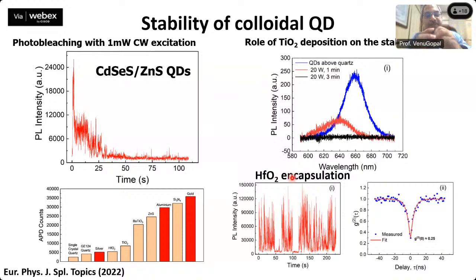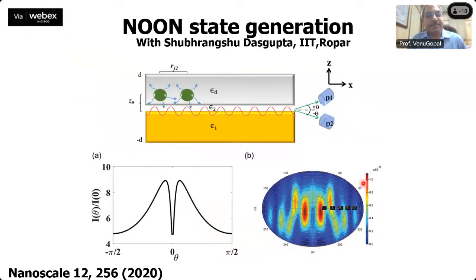Blinking happens for these nanoparticles because the surface is a defect. Any electron which reaches the surface state stays there for a long time, and because of that the emission gets suppressed for a certain time, till the electron goes back into the nanoparticle. So we showed that we can improve on the blinking, the times reduced, and we showed single photon emission from these structures. We have proposed a simple structure where you put two quantum dots inside a dielectric